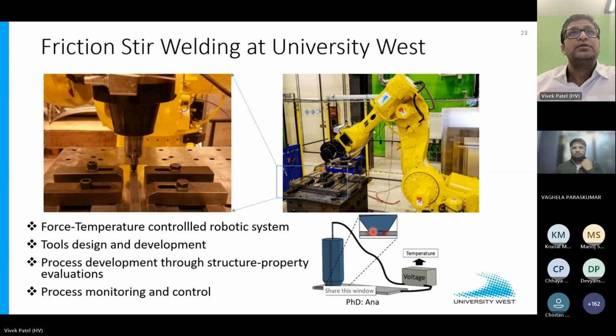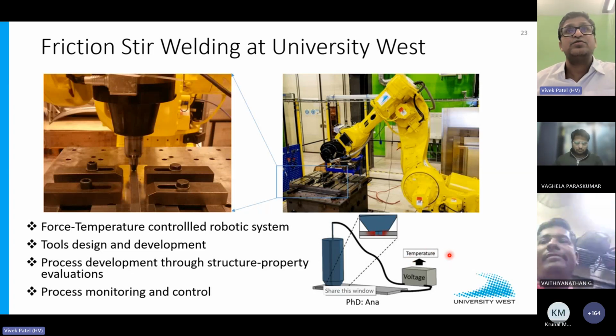So this robust system developed by the PhD graduates will make sure that the other parameters, like rotation speed, if you recall the previous slides, the process variables, the 3 red arrows, those 3 red arrows are changed to keep the temperature constant. So we ensure there is no defect.